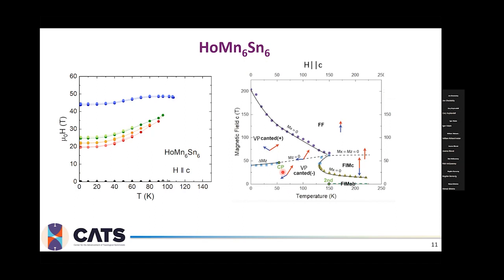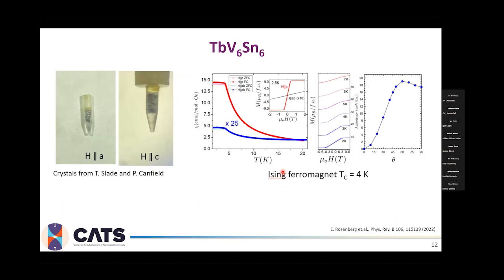phase diagram. The other example which we thought would be interesting is terbium vanadium 6 tin 6. This is one of the Ising ferromagnets with a transition temperature of 4 Kelvin. In that case, to measure along the A direction, we just needed 1 crystal placed in an ampule. However, since the crystals were very thin, I stacked together around 10 to 15 pieces in this ampule to measure it along the C direction.